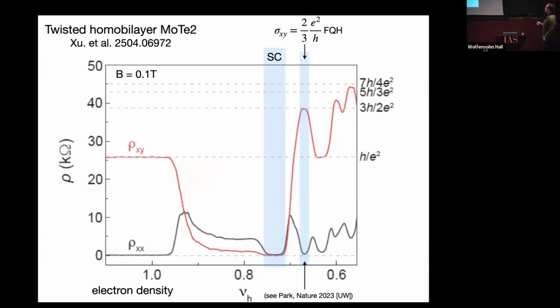So this is an example of what line traces of the transport data look like. We're going to be showing here Hall resistance and longitudinal resistance as a function of electron number. Here's the superconductor. It's dissipationless and has no Hall resistance. That's a superconductor. And then you do this tiny change in electron density. Then you have a state which is dissipationless but has a fractional quantum Hall effect. So I think this is quite amazing that these are like the 2 great dissipationless effects in quantum condensed many-body physics occurring right there in the same sample with this tiny change in density.